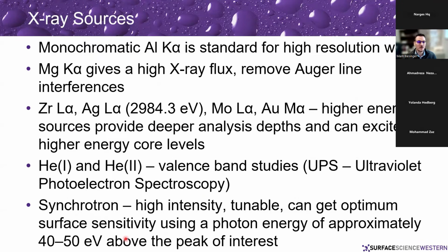You can also have helium-1 or helium-2 ultraviolet light, which is used for ultraviolet photoelectron spectroscopy. Or you can also use a synchrotron, which has a high-intensity tunable source, and you can tune that to get your optimal surface sensitivity, generally using a photon energy of approximately 40 to 50 eV above the peak of interest.